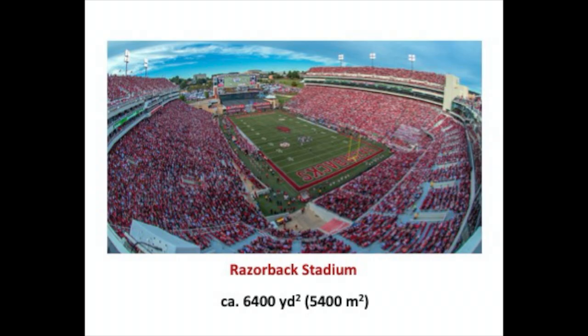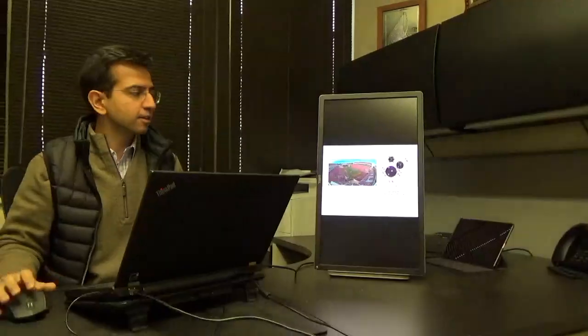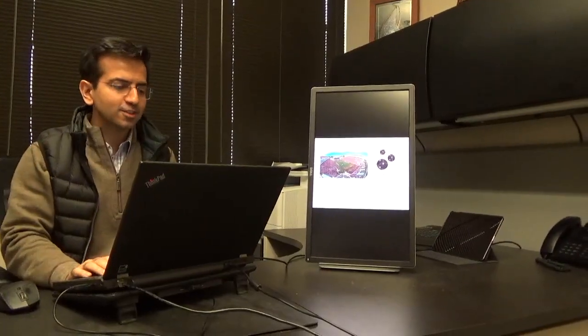For example, this is the Razorback Stadium at the University of Arkansas in Fayetteville, and the surface area of the field is just 5,400 square meters. So this 1 gram of this material has a higher surface area. If we were able to stretch this out, it would fully cover the field and would have even extra surface.